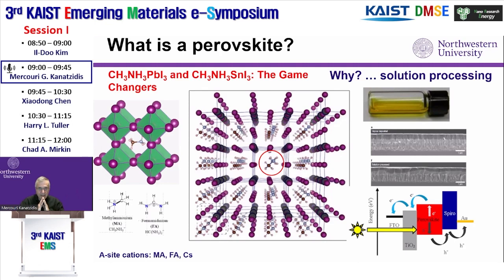In the case of halides, the most important perovskites are the lead halides and the tin halides. And they make this anionic framework. Lead is 2+ and tin is 2+. And this network makes cages, and because it's anionic, it needs to be charge balanced. And so it has an extra cation in the cages.